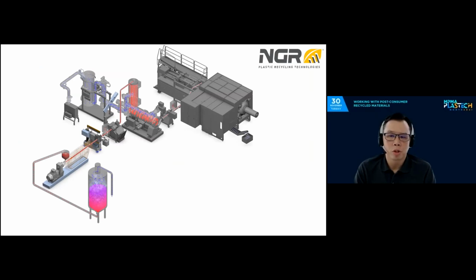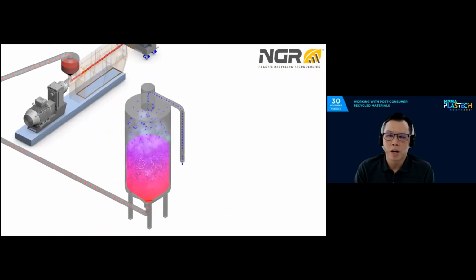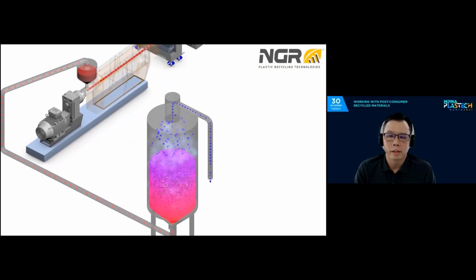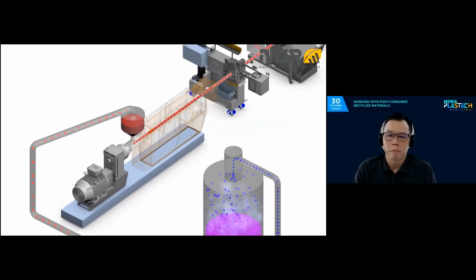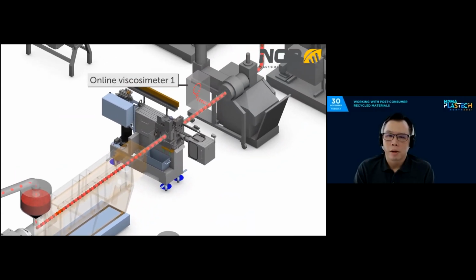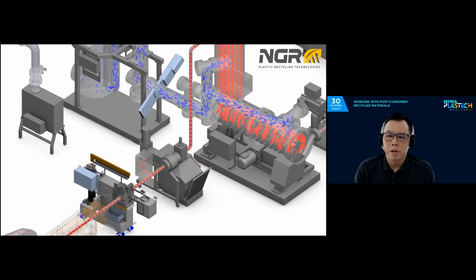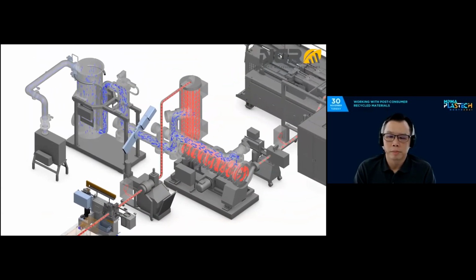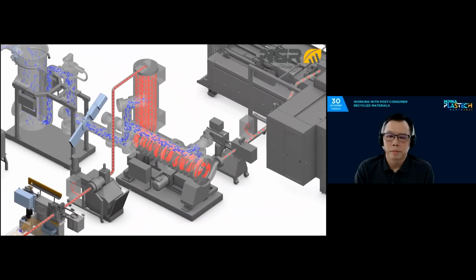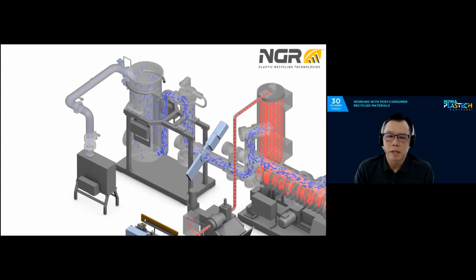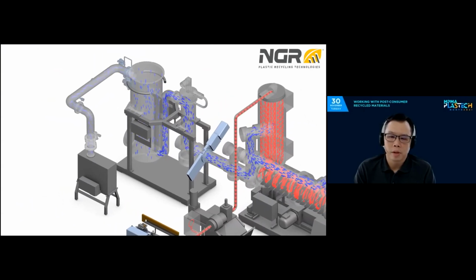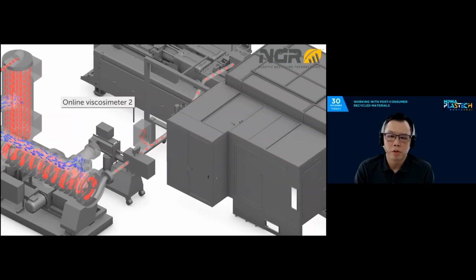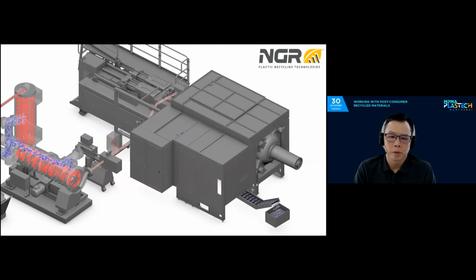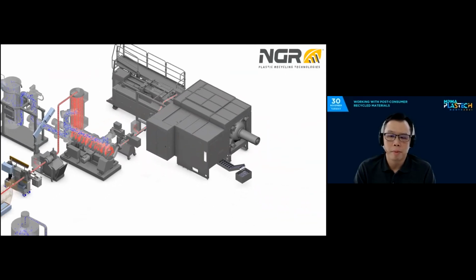This is a process from which post-wash PET bottle flakes are made directly into preforms. Washed PET bottle flakes are first pre-dried in order to remove any excess moisture. Then the bottle flakes are melted in the extruder before being filtered by the first melt filter. The melt enters the P-React system for decontamination and viscosity lift. The volatiles are then extracted and filtered via a condensation system. The decontaminated melt goes through a final melt filtration before entering the injection molding machine. The molding machine in this case produces preforms, which could then be made into beverage bottles.